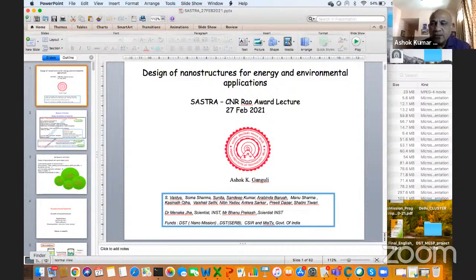Yeah, so it's a very good question. See, the efficiency that we are trying to increase will not be good if your interface is not good. The ones which I showed are the best interfaces that we got. But when you do research, you will get lots of interfaces where there will be gaps. There will be what is very important in physics, they call interdiffusion of ions. That means from one side, ions will move to the other side, and the other side's ions will come to this side. This interdiffusion you have to reduce. That is a very key point, a very important point.